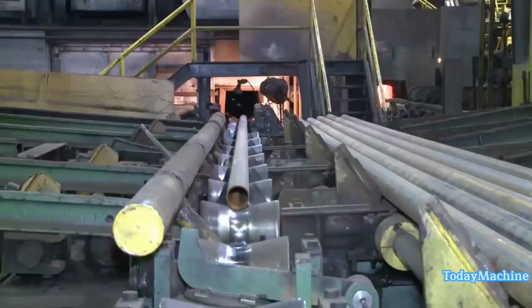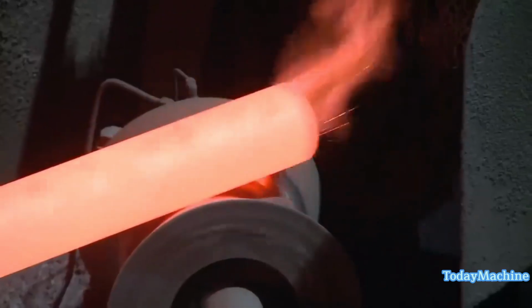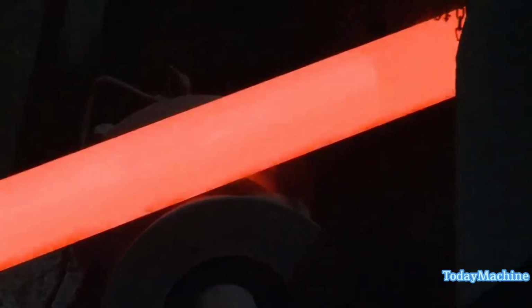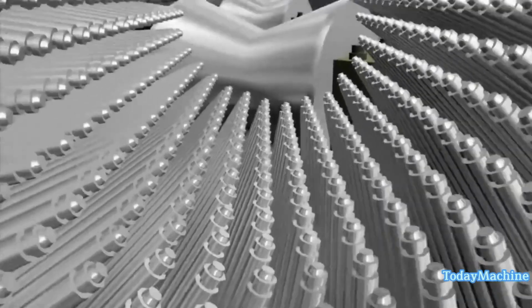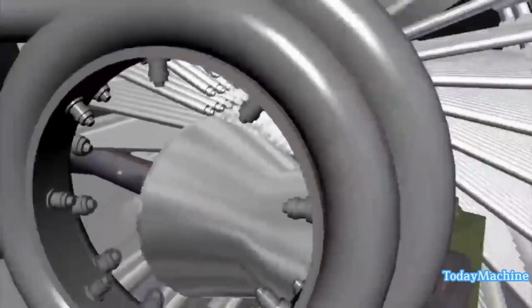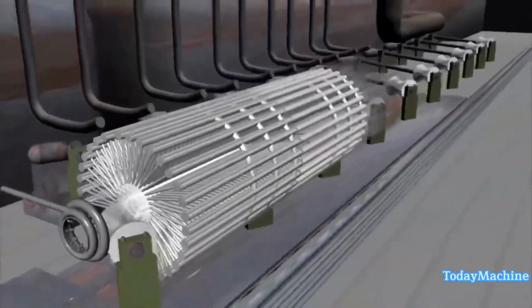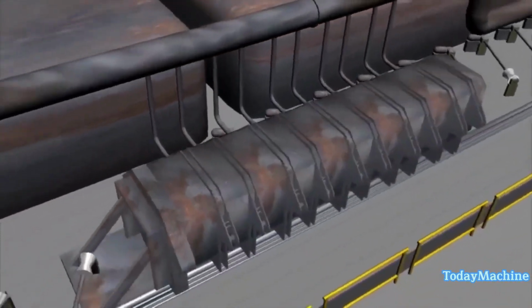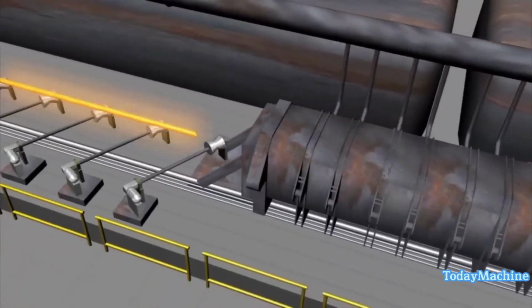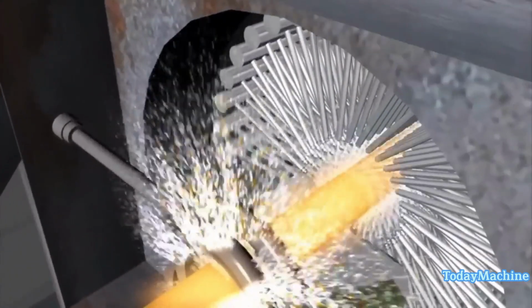In the heat treatment line, the pipes are heated to 870 degrees Celsius in a walking beam preheat and quench furnace. After reheating, the pipes pass through a water spray quench unit consisting of 7 spray quench heads with 800 individual water nozzles. The high-pressure water evenly applies the quench to the rotating pipe.